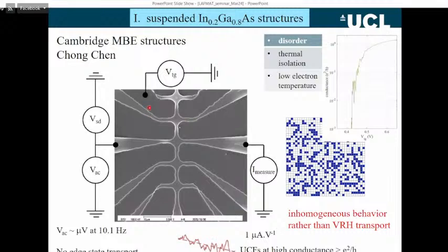We can apply AC voltages and DC voltages, and we can measure currents. We've also got a top gate on here, so the SEM image is looking through a top gate. We can apply gate voltages and change the carrier densities in the system, also moving the chemical potential around in the density of states. So we have disorder, we have thermal isolation, we have low electron temperatures.